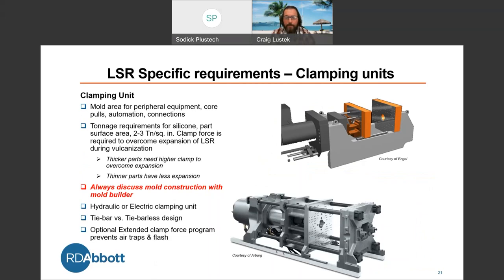Looking at clamping units, the clamping unit for LSR is a bit different because silicone, as it heats, it expands. So we want to make sure that we have enough clamping force to hold back that expansion of the part. So we're looking at tonnage requirements for silicone. We want to calculate out the surface area, and then we always want to multiply that by 2 to 3 tons per square inch. And again, that is needed to overcome that expansion of the LSR material. So your thicker parts need a higher clamp, while your thinner parts don't need as high a clamp because there's less expansion.